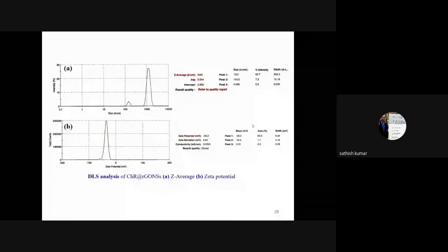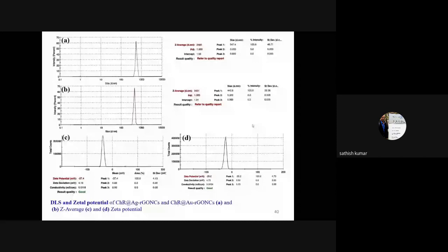Again, we have studied the stability of the nanoparticles, and here you can see that as compared to the individual silver and gold nanoparticles, the reduced graphene oxide has a large negative zeta value, which clearly indicates that the nanosheets are highly stable. For the silver and gold nanoparticles also, with the presence of the reduced graphene oxide nanosheets, the surface charge is increased. This means the nanoparticles decorated on the surface of the reduced graphene oxide nanosheets in the composite are more stable than the individual nanoparticles.